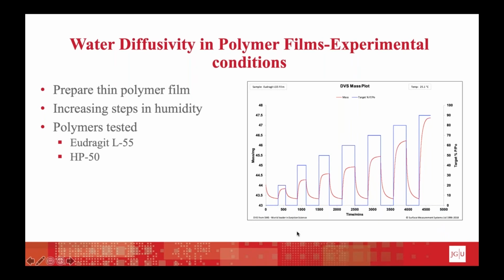The polymers used in our experiment were the Eudragit L55 and HP-50. These two types of polymers are usually used as enteric coating, but of course an additional benefit of them would be the protection against moisture. So what I did was I prepared some thin polymer films by film casting from organic solution, and then put these polymer film fragments into the DVS apparatus and ran cycles like displayed here in this image.